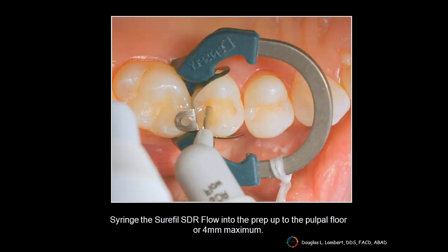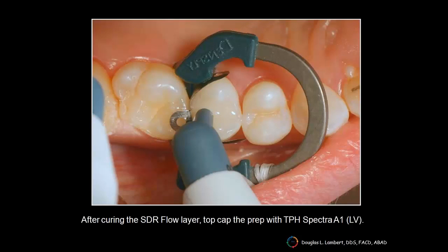And then here's the newer technology SureFill SDR flow flowable that's allowed to be placed in a bulk increment to 4 millimeters in height. Usually that's a good ratio, up to the height of the pulpal floor. And let that flow into the preparation, cure it through the tooth from the buccal and the lingual, then place a little more flowable on top of that hardened layer. Don't cure that little bit of flowable, and then add the body composite, in this particular case TPH Spectra A1, right on top of the preparation, completing and filling the prep.